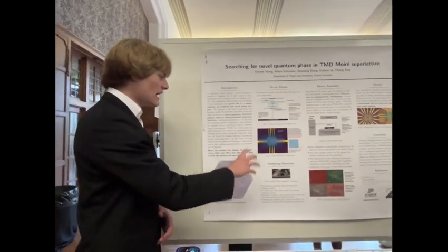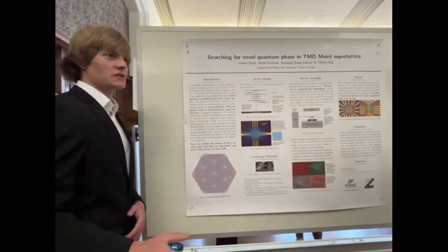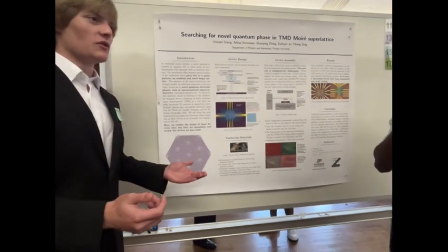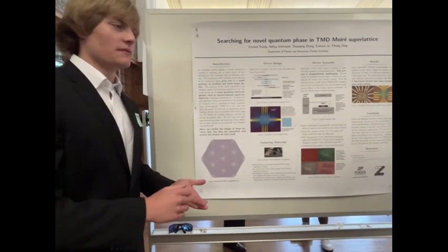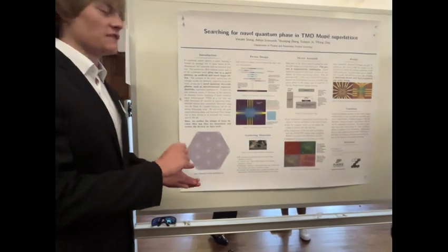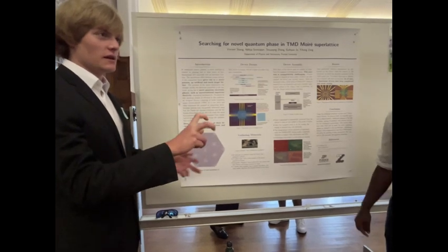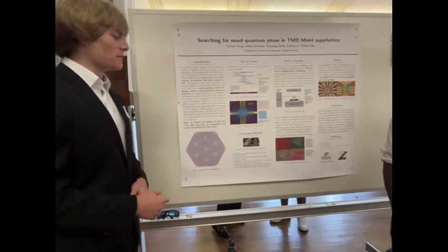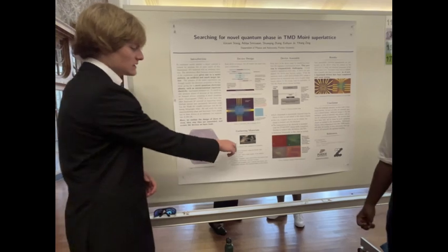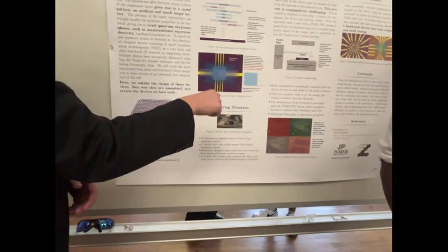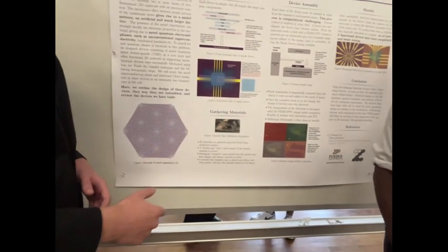But to gather the materials to do this is a challenge of its own. We use the Scotch tape exfoliation method. So say you start out with hundreds and hundreds of layers of graphene or graphite, and you want monolayer graphene, you put it onto tape, you peel another piece of tape off, so a daughter tape from the mother tape, and you keep repeating that process until it's so thin, and this is what's happening here. Then when you place the tape onto silicon and peel it back off, it deposits 2D material onto the silicon.